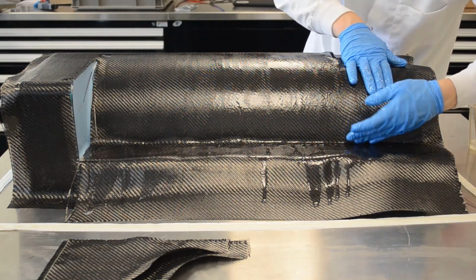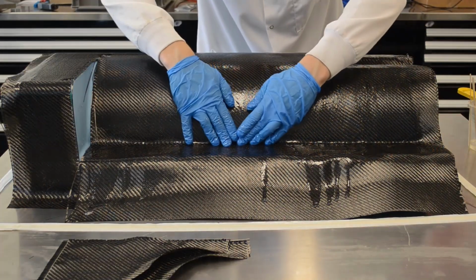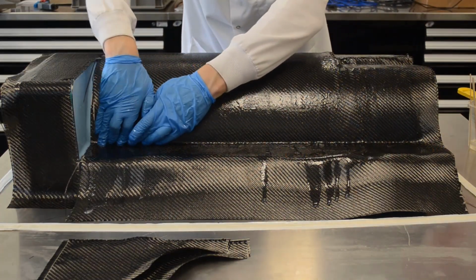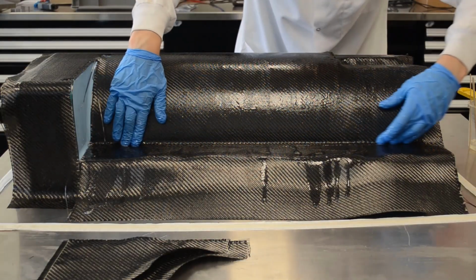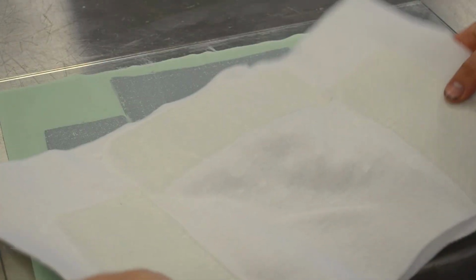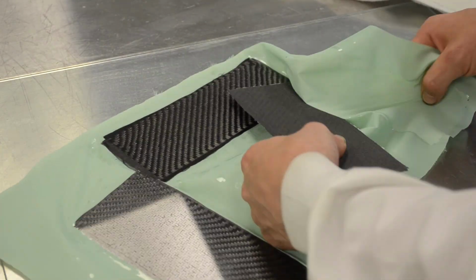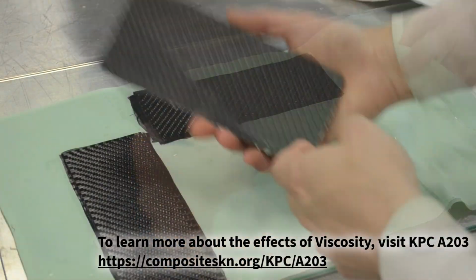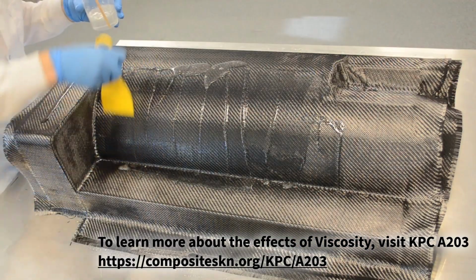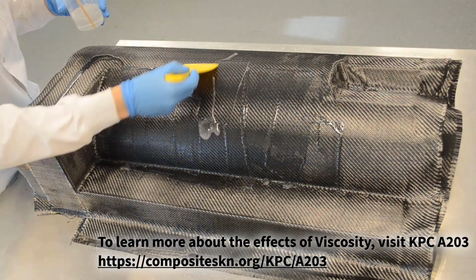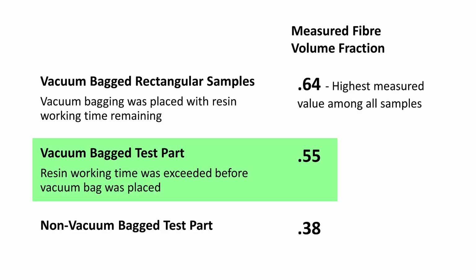The same resin was used as the previous wet layup part, with a working life of 20 to 25 minutes. Switching to a longer working life resin gives more time to precisely position and saturate the fabric before pulling vacuum. The working life of the resin can also have an effect on fiber volume fraction. If the vacuum consumables are placed and vacuum is pulled after the working life of the resin has been surpassed, it will have an increased viscosity and will not flow into the consumables as readily. Excess resin will stay in the part and reduce fiber volume fraction. This part achieved a fiber content lower than some of our previous test samples, which were vacuum bagged before the working life of the resin had been exceeded.